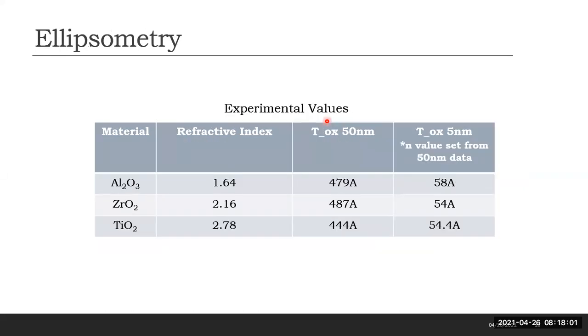The refractive indices obtained from the experiment were slightly lower than the literature values. This could indicate a slightly different stoichiometry, that is, the atomic ratios are slightly different, which might be due to the relatively low deposition temperatures in ALD.